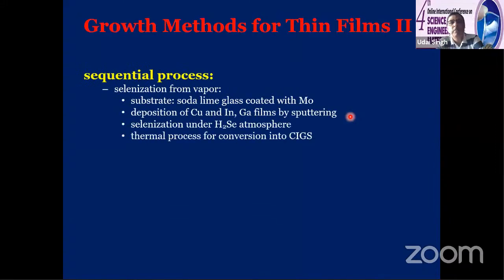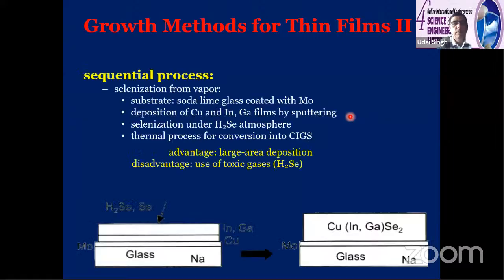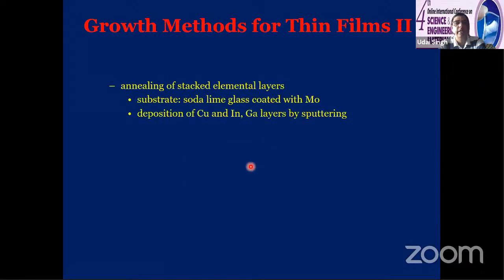The other method is the sequential process, which is like selenization from the vapor. So you take the substrate, you deposit the moly, and then you sputter the copper, indium, and gallium. You get different alloys also, and then you selenize. Initially, when you selenize in hydrogen selenide, it gives the highest efficiency. But hydrogen selenide is very toxic in nature, so people try to avoid this because in a university or research lab it is generally not advisable unless you have certain precautions. In India, not much precaution is being taken. So it's not advisable to use this hydrogen selenide.